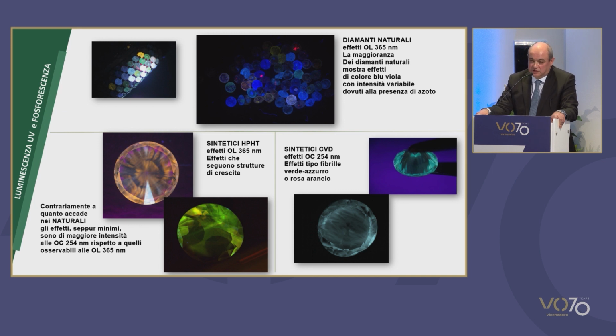Well, we have seen that in 98% of cases, natural diamonds are of type 1. When nitrogen is present in the diamond, we have UV fluorescence, so if you expose a diamond to ultraviolet light, in the vast majority of cases, the diamond will produce a luminescence or fluorescence, which is blue purple in color. So if you have diamonds, you put them under the light and you see a blue color like the one that you see in the top center slide, or a purple color, then you can be sure that the diamonds you have in front of you are natural. They cannot be synthetic. But if you see strange colors, then you should start worrying.